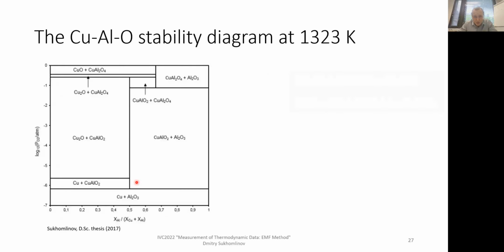And that's the diagram for the ternary system. Copper, aluminum, oxygen. It's a stability diagram at 1323 K. So at the bottom, on the x-axis, we have mole fraction of aluminum, and then the vertical axis is oxygen partial pressure. At low oxygen partial pressures, alumina is a very stable oxide, present as alumina, but copper is metallic.